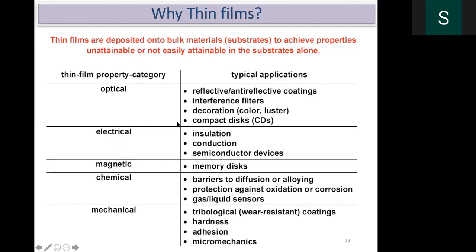So they can be used as reflective or anti-reflective coatings, and particularly for decoration. In the case of Titan watches, the rings are coated with titanium nitride. You know, titanium nitride is a very hard material, more than 25 GPa in hardness. It cannot be scratched by any other hard materials like steel or iron or whatever alloys of iron.